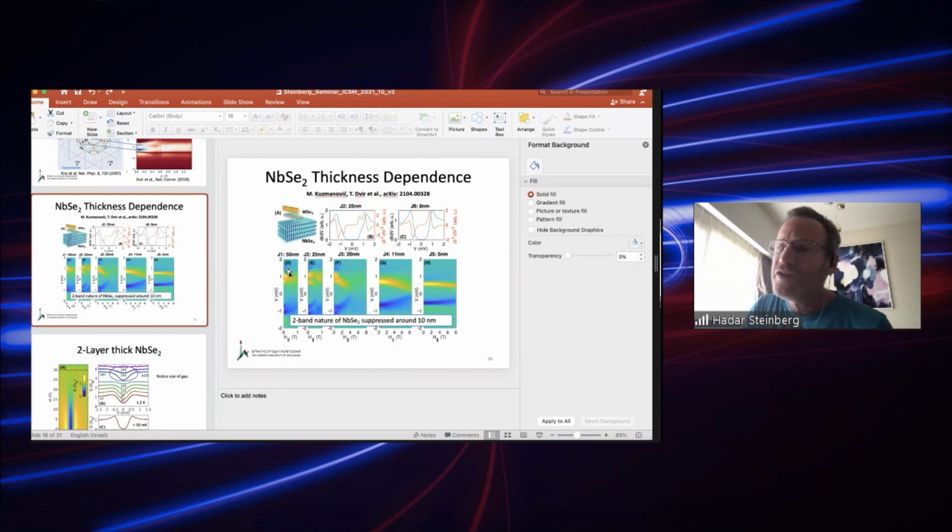At 25, 50 nanometers, you have a very dominant orbital component, and this orbital component is going to depair, albeit at different rates, the carriers of the niobium and the selenium carriers. The Ising kicks in only at a very, very thin limit once you have suppressed all other sources of depairing in the system. And you have to be somewhere below a few nanometers, the few layers, for this to be observable. So everything I've been showing about this differentiation of selenium and niobium, that's a finite thickness of the sample. Thank you.